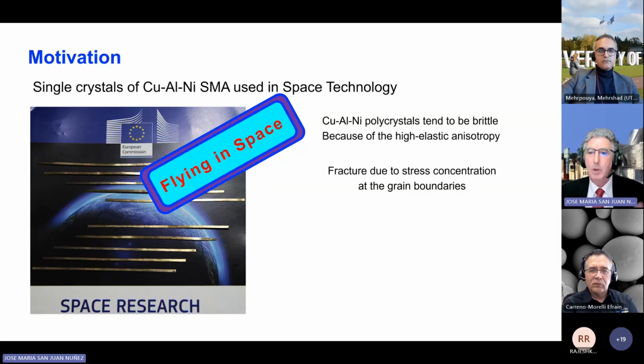And this is a general property in all copper-aluminum-based alloys, like copper-aluminum-manganese, copper-aluminum-beryllium, and so on, because it's coming from the high elastic anisotropy of these alloys. Because of this elastic anisotropy, for instance, the elastic modulus in the 1-1-1 direction is 10 times higher than the elastic modulus in 001. This enormous elastic anisotropy makes a concentration of stress at the grain boundaries, and the fracture in polycrystals is due to the stress concentration at the grain boundaries.